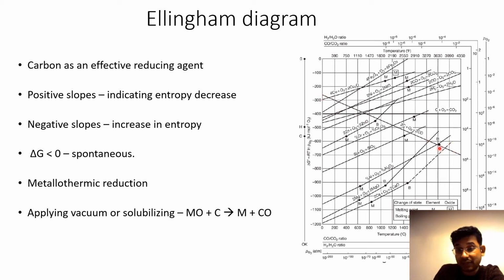And there is one particular line with a negative slope, and this is, without any exaggeration, one of the most important lines in metallurgy. You have carbon plus oxygen giving you carbon monoxide, and the intersection points of this line with the various metal oxide lines give you the temperature at which carbon can reduce these oxides back into metals. So using carbon to reduce these oxides back into metals is very important in metallurgy.